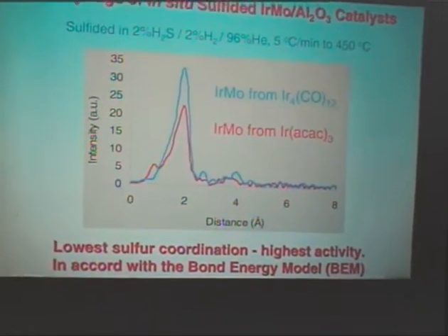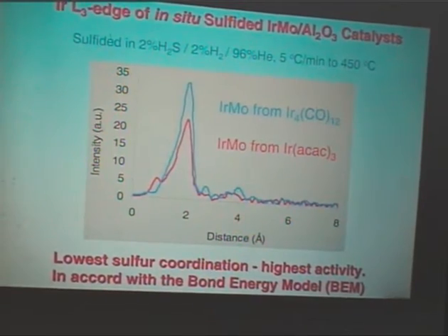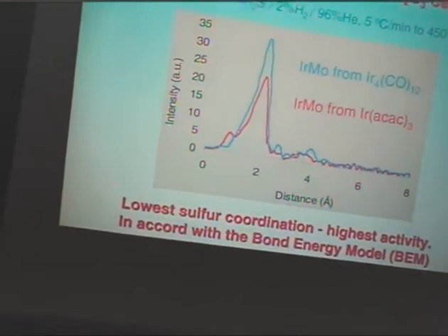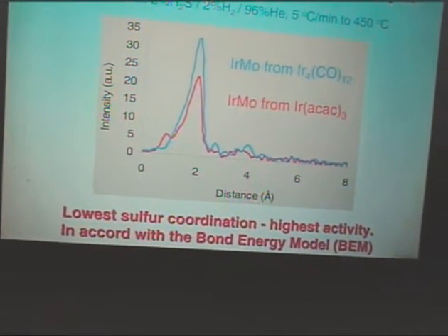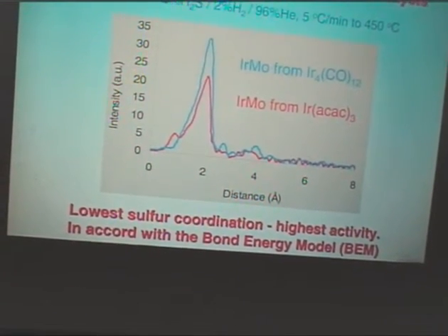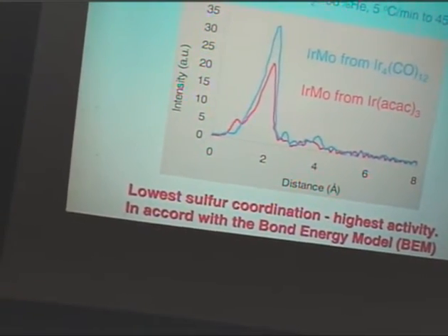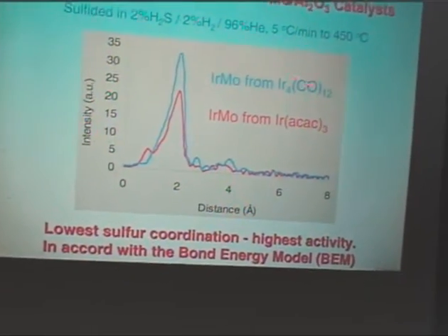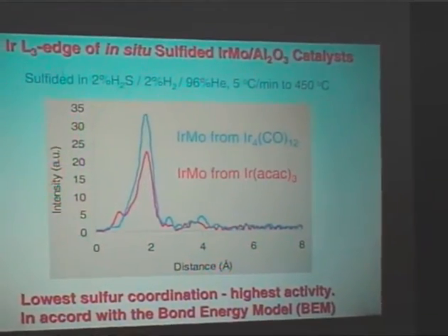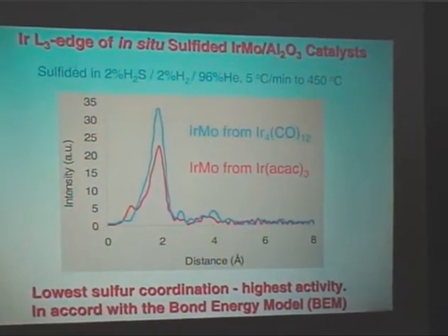And we also carried out EXAFS for the iridium edge. And here we found some interesting differences. The coordination for iridium from this iridium carbonyl system is much higher than for the second system originating from iridium acetylacetonate.